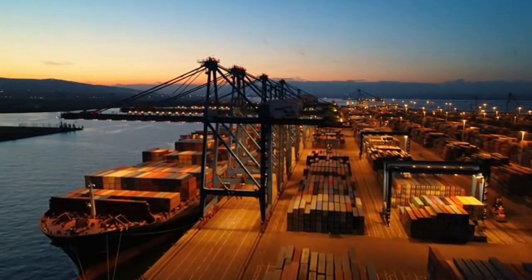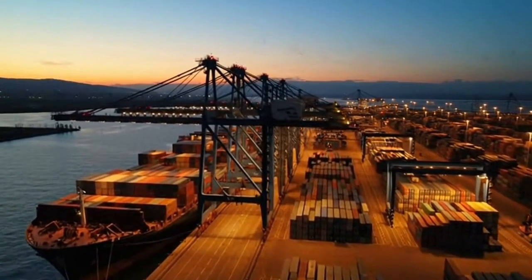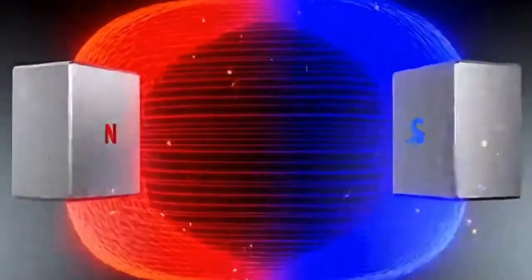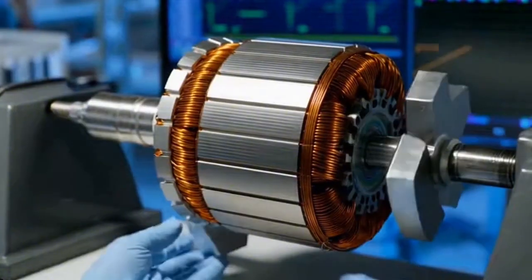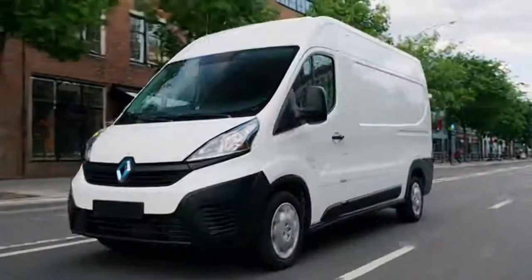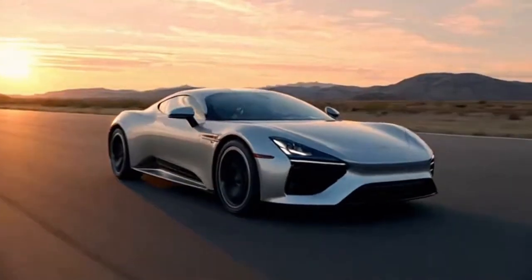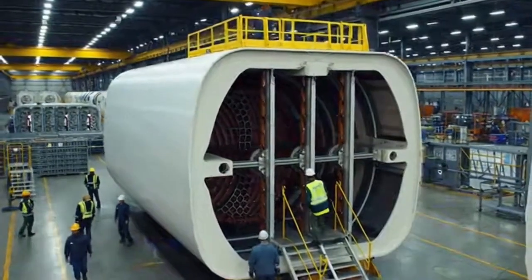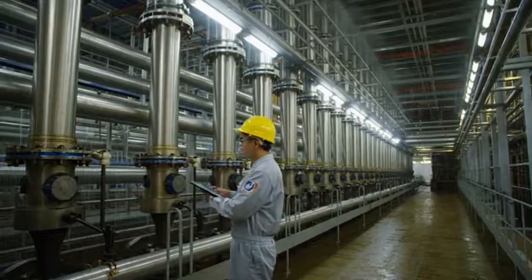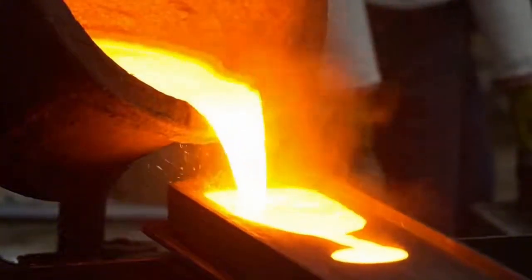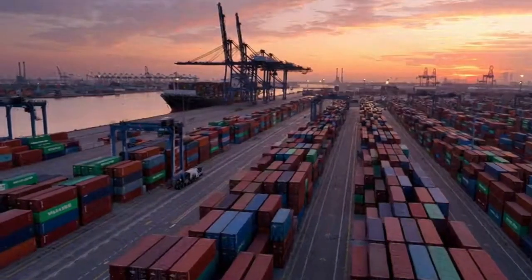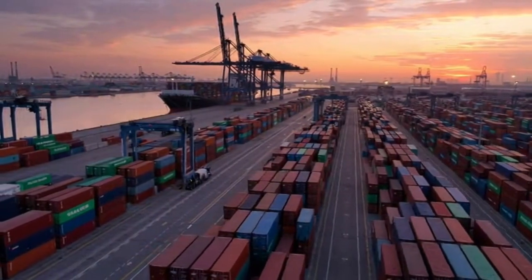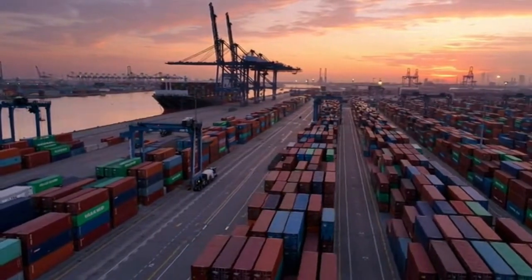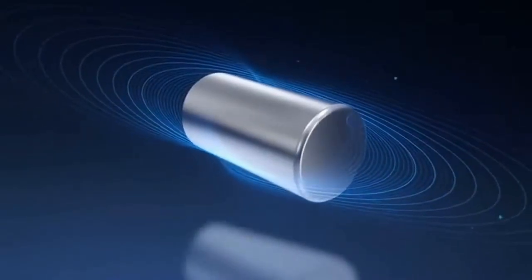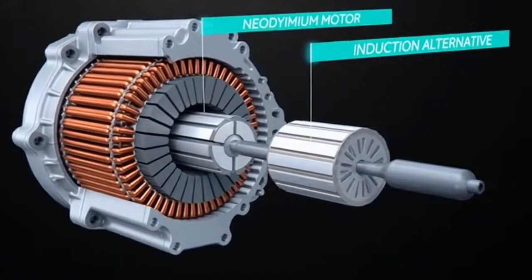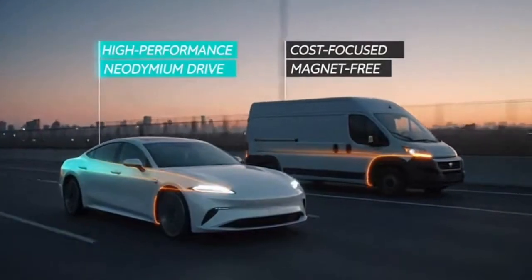Start with separation, the step where you pull the rare earth elements apart. On paper the chemistry looks almost mundane. Mix phases, let ions partition between them, repeat. But making thousands of tons per year of neodymium oxide at 5 nines purity, 99.999% pure, give or take, while simultaneously producing praseodymium, dysprosium, and terbium to spec on adjacent lines is a control problem and a capital problem. It's not a textbook operation, it's an operation that lives or dies by on-the-job